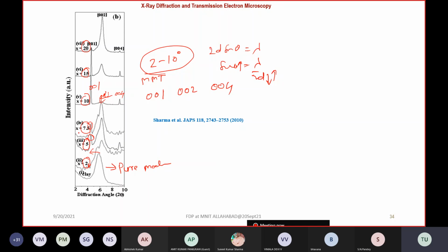It gives a clear indication that after the cation coordinated polymer enters the clay channel, the clay channels are broadened and their size is increased. This is shown by X-ray diffraction analysis. But the scientific community is clever and will not believe one characterization technique. You are supposed to endorse your characterization results with a number of techniques.